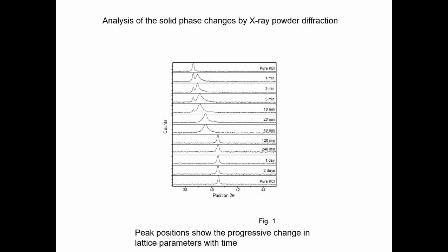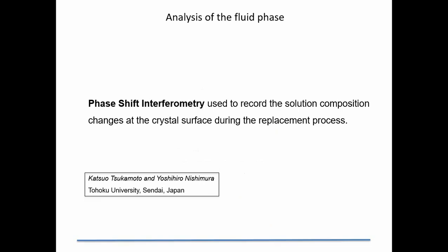Start off with pure KBr. There's the powder X-ray diffraction peak, and then we move across until we get pure KCl, and the intermediate phases along the solid solution KBr, KCl range. So that was the solid composition. What about the fluid? What's happening to the fluid?